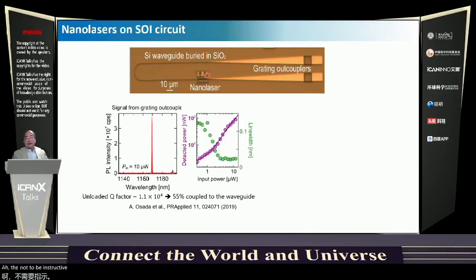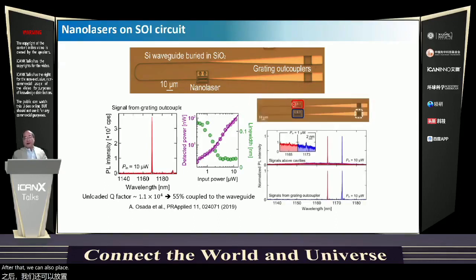So indeed, this is the nanobeam laser structure, nanolasers, and this is the silicon waveguide. And these are grating output couplers. And if we place one laser here, we can see lasing oscillation from the output couplers. And this is ideal characteristics. And after that, we can also place another laser by using transfer printing. Then we have the lasing oscillation again with different lasing wavelengths. This spectrum is measured from above the samples, and this is measured through the waveguide and also output couplers, and so on.